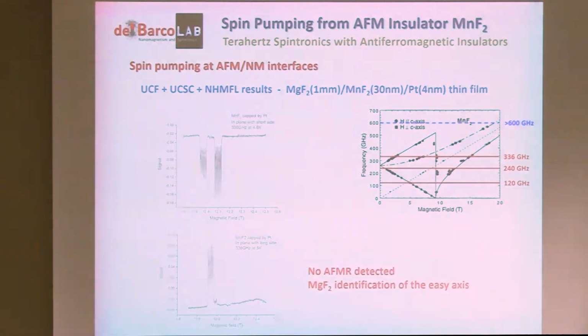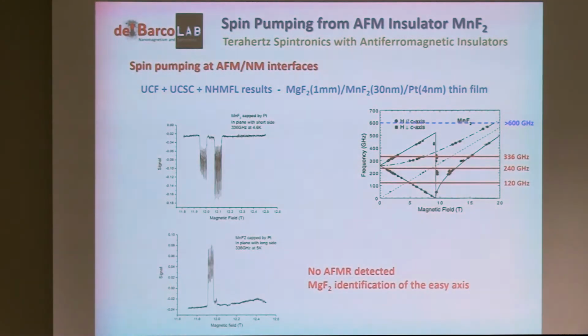And the first thing that we did was to try to do spectroscopy, just to look whether we are able to do this same experiment at, in this case, 336 gigahertz, and see whether we see a peak here, another peak here, another peak there, right? Absorption of microwaves. We didn't see anything. What we see here is something totally unrelated to that, but it allows us to determine where the anisotropy axis is. But this is just manganese impurities in the substrate. But we didn't see the peaks that we were expecting.